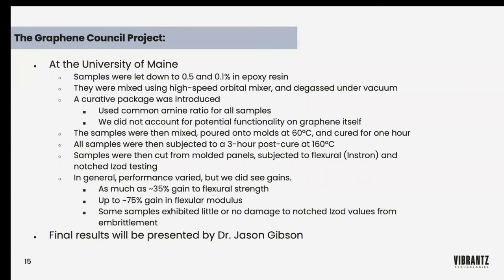At the University of Maine, I'll give you an overview of what was done, and then Jason will be speaking specifically to the results. At the University of Maine, the samples were let down from our master batches to concentrations of 0.5 and 0.1% in Bis-F epoxy resin. After they were let down into the resin, they were mixed using a high-speed orbital mixer and degassed under vacuum. Once that step was accomplished, a curative package was introduced.